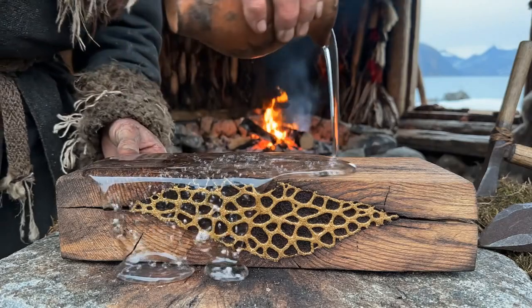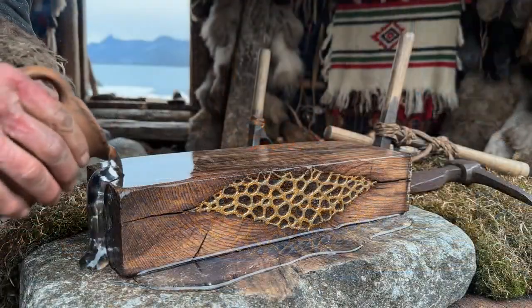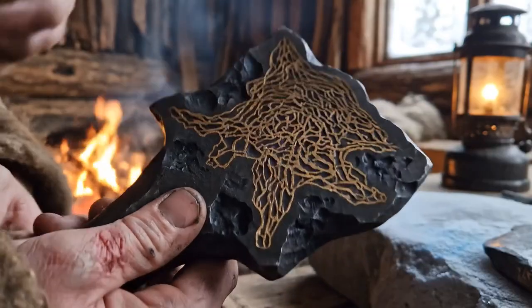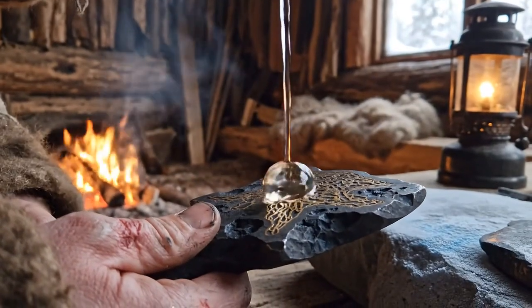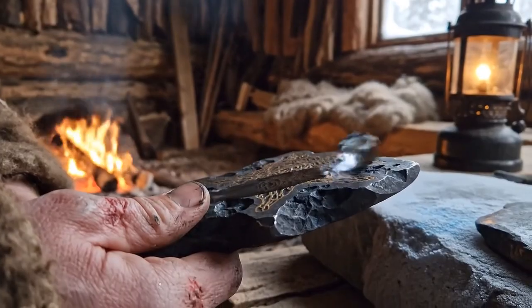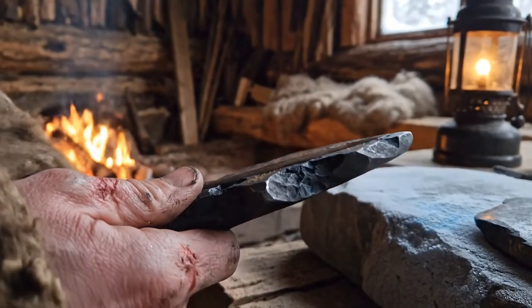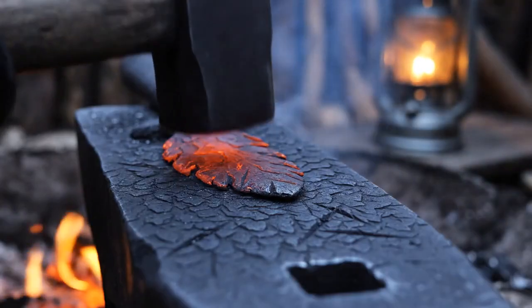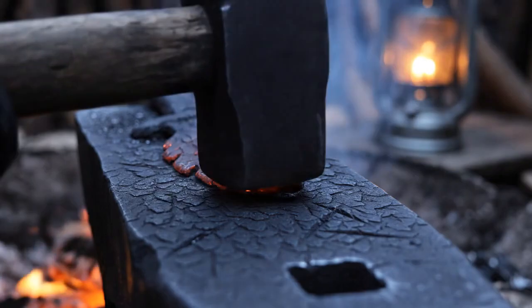The crews whose iron survived, the Gokstad ship's iron fittings, still structurally sound after 11 centuries, applied oil to hot metal. Specifically, metal hot enough to make the oil smoke the instant it makes contact. Not burning. Smoking. That temperature is what creates the bond. Here is why that works.